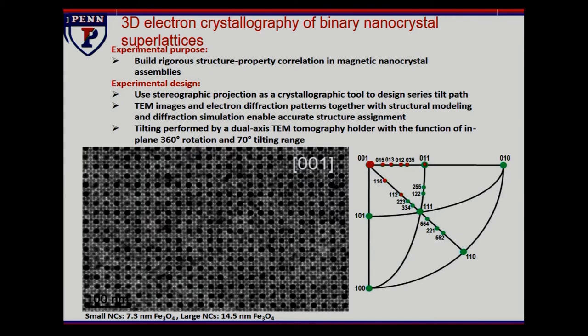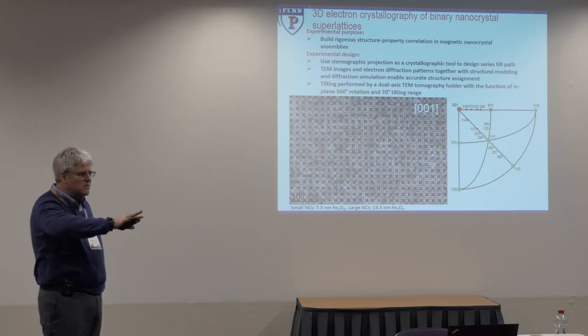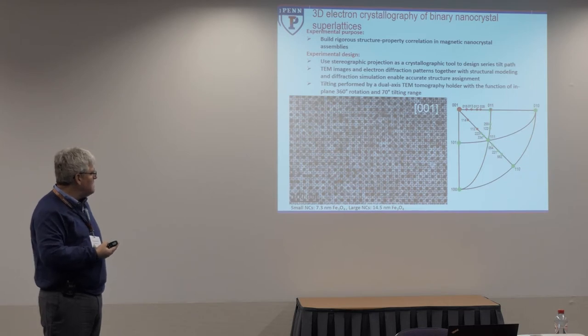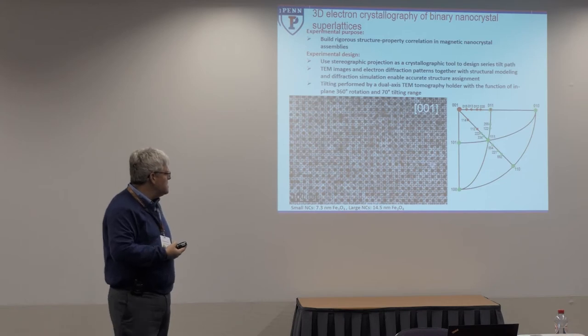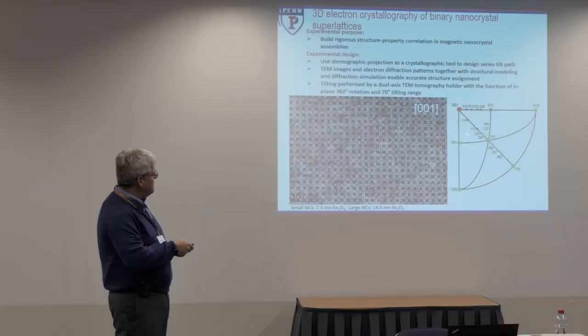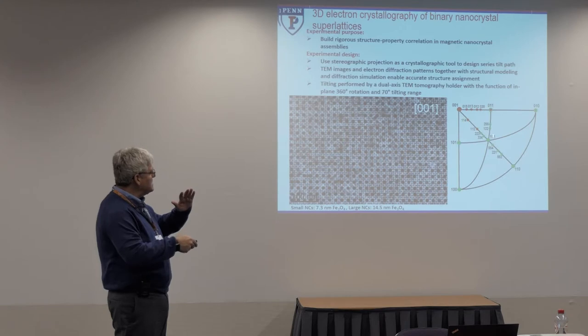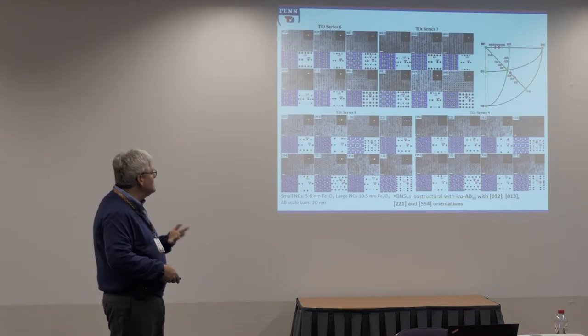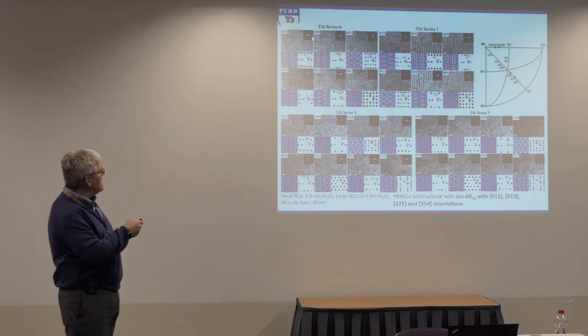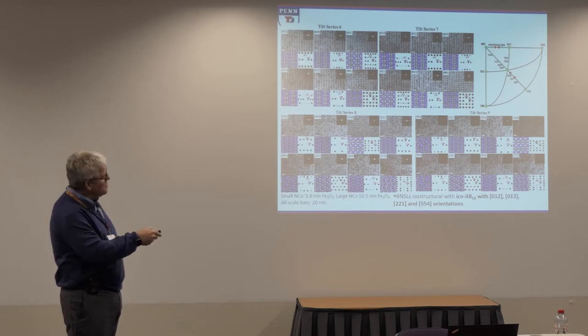So these types of superlattice structures, you can do the crystallography, so tilting the sample, looking at different crystal phases. So we spend a lot of time doing this kind of work, and I'm not going to drag you through it too much. But what I want to put forward is this idea that it's a good transition point to begin using the formalism and the treatment that you would in materials science characterization of any normal inorganic material, and to map that description onto these types of superassemblies. So this is a stereo projection that shows the march as we change the tilt angle and go through the three-dimensional crystal's alignment. And if we've done this right, as we tilt the sample and look at the images and the diffraction data, we should be able to map out each of the major crystal axes, just like we would with a normal single crystal. And so when you do that, you can compare the real space images and the diffraction images to simulations of the same as you march through all of these different axes.